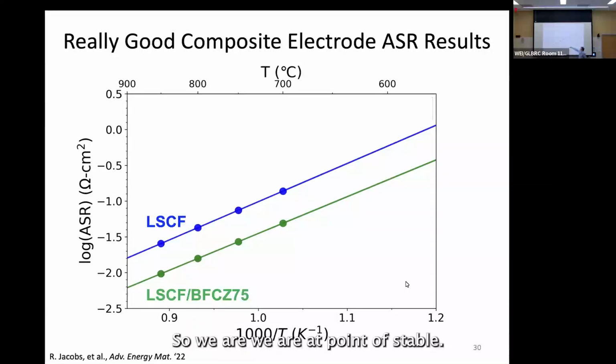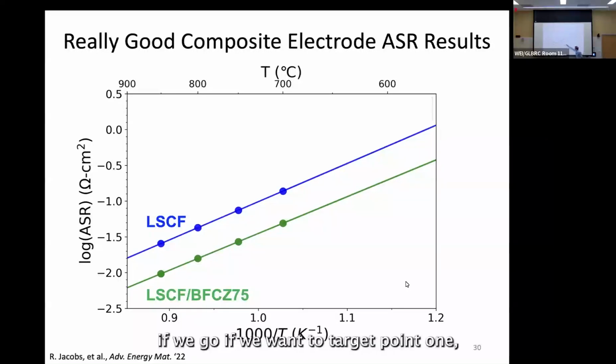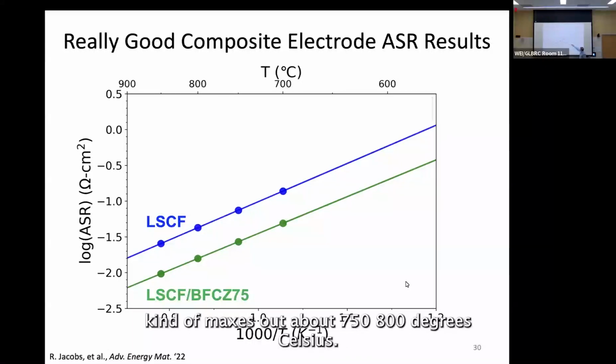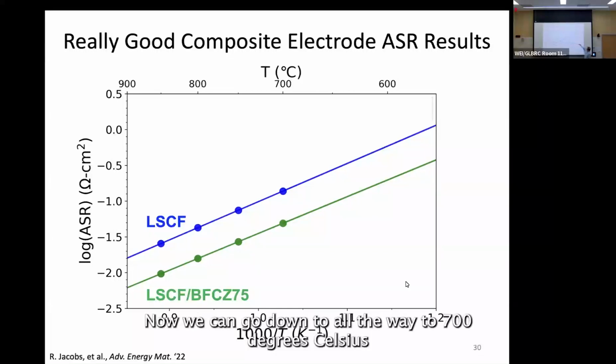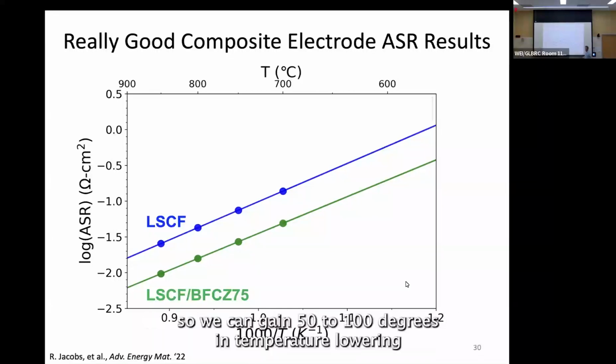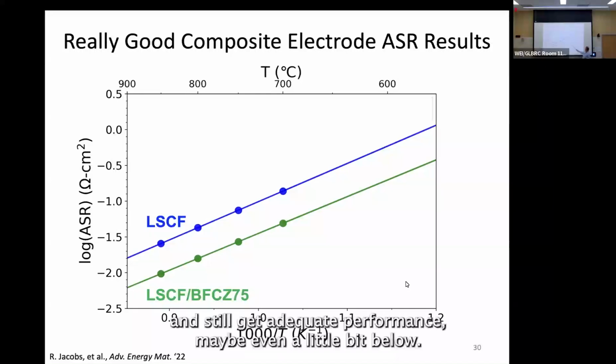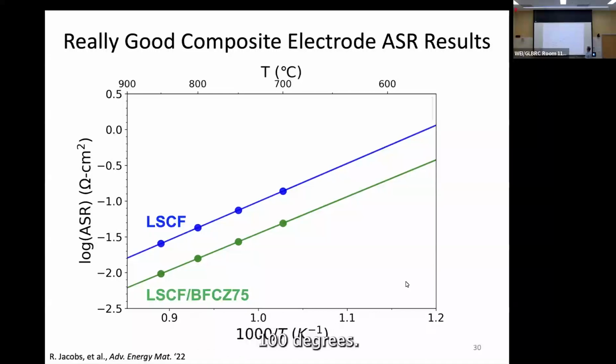If you're up near 800 Celsius, this is now a log scale. If you're up near 900, we are at 0.01 in terms of area-specific resistance. If we want to target 0.1, lanthanum, strontium, iron, cobalt kind of maxes out at about 750, 800 degrees Celsius. Now we can go all the way down to 700 degrees Celsius. So we can gain 50 to 100 degrees in temperature lowering and still get adequate performance, maybe even a little bit below 100 degrees.